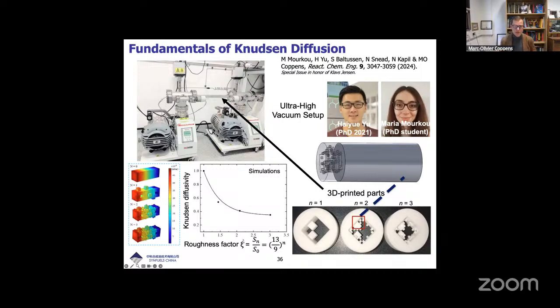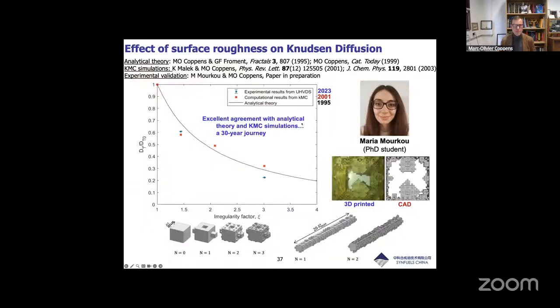And so Maria did experiments on this. And so this is basically the answer of a 30-year journey for me. This shows this 3D printed image based on CAD, different pores of different lengths. And what you see here is the diffusivity measured. These are the blue points, the computational results for kinetic Monte Carlo in red, and the analytical theory, where you see that we have experimental validation.